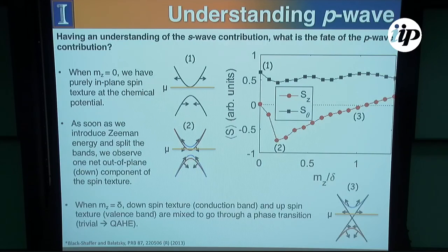And so what I've done is I've calculated exactly what's happening with both the S in-plane components and out-of-plane components. The thing that's nice about this is it clearly illustrates why I thought it was going to be very difficult to find topological superconductivity in these systems, because when you actually start adding in the Zeeman term, you don't just separate spin states. You can separate that in the bulk, that's no problem. But what happens in the surface states is you start canting spins. And so as soon as you turn on a Zeeman field, you get an out-of-plane component that gives you an